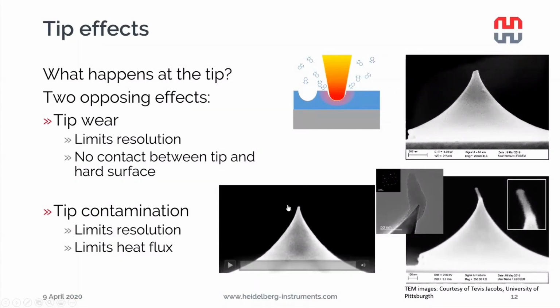Basically, instead of this nice sharp tip, we get a blunter tip that limits our resolution because the tip diameter is bigger. This usually is not such a big issue for us because the tip is never, or rarely ever, in contact with the hard surface of the substrate. It usually is only in contact with the soft resist material, and tip wear doesn't happen that much. The main issue that we know of is the tip contamination. This limits our resolution as we start to grow something on the tip, but this also increases the tip diameter. And it also limits our heat flux, as this contamination often seems to be insulating and we get worse heat